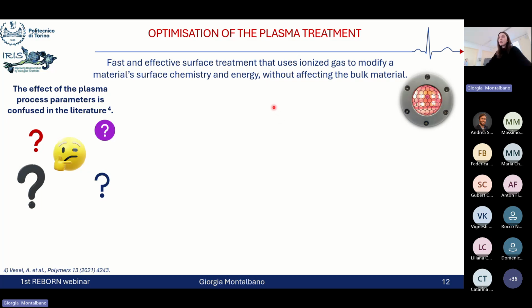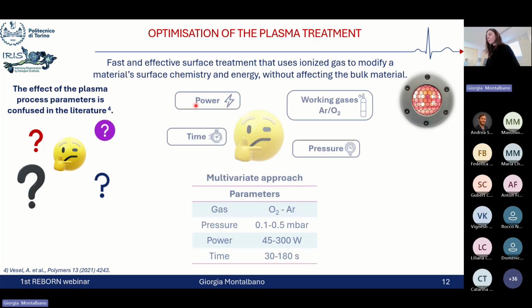However, the effect of plasma treatment and the different process parameters are quite confused in the literature, especially when we look at polymeric substrates. So based on this, we decided to adopt a multivariate approach in order to test and explore different combinations of the different process parameters, looking at different power levels, exposure times, pressure values, and in terms of working gases, since we are working with PVDF, in order to make our surface more hydrophilic, we selected oxygen, possibly in combination with argon, in order to stabilize the overall process.